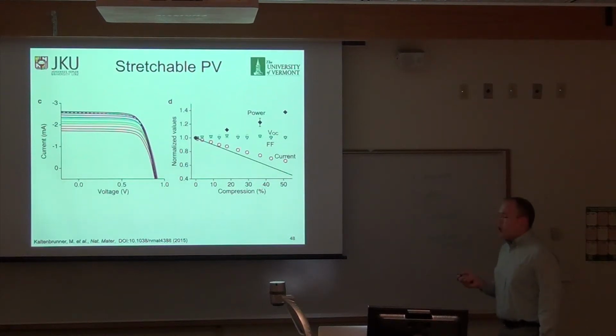If the current were to track exactly with the compression ratio, you would expect the current to decrease along this flat line here. So what you're seeing is actually an increase in the performance of the device because you are collecting more of the photons that are emitted.